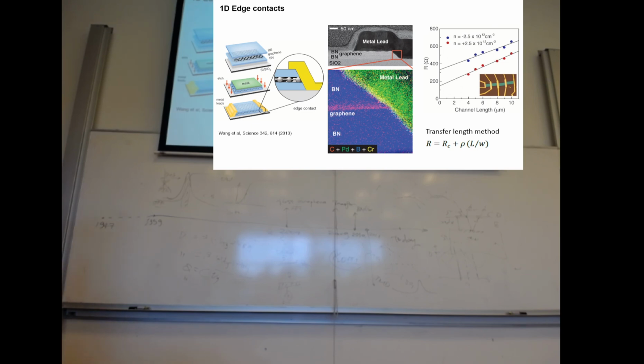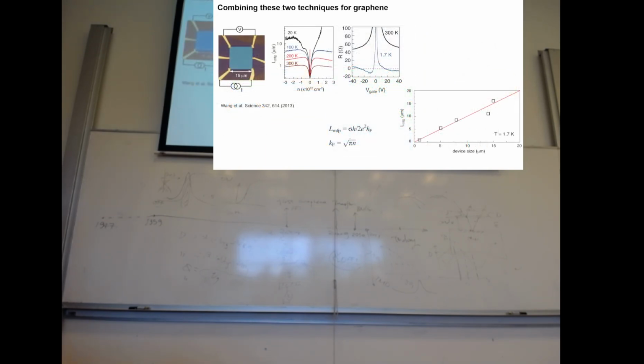And this is how it looks under the TEM microscope. You have boron nitride on top and boron nitride on the bottom, and graphene in the middle. You put a metallic contact using this side contact technology, and the contact resistance is very low, ohmic, and you will have a mean free path that is amazingly large. For example, with a device size of 20 micron, you almost have a mean free path of 20 micron. So it's limited by the size of your device, not by scattering anymore. Of course, that is at low temperature, because at high temperature you still have phonon scattering, which cannot be killed by the substrate.